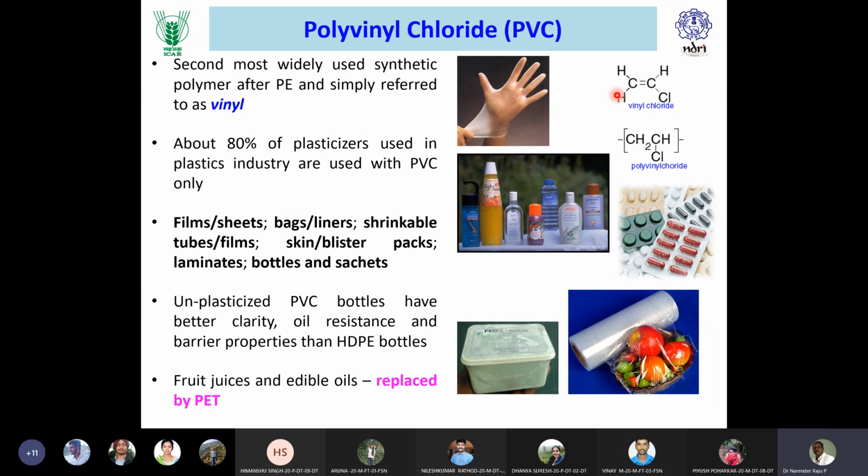Now, when you try to process this polyvinyl chloride, HCl constantly gets released from this material, and this continuous HCl release leads the polymer to become yellow in the beginning, right? And then orange. Further heat treatment leads to red color, later brown, and ultimately black color. And the color variation will tell the intensity of heat that was given to such materials.